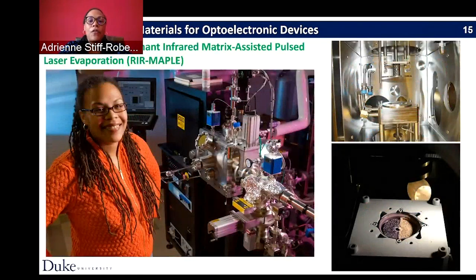But I needed a way to deposit those. And so this is what I developed during the course of my research program at Duke. And it's a variation of pulsed laser deposition. So it's called emulsion-based resonant infrared matrix-assisted pulsed laser evaporation. And this is a picture of the system that I have at Duke. I have the growth chamber and load lock chamber, and the laser is sitting in the black box. And this variation of pulsed laser deposition will allow the control and deposition of these hybrid materials in a way that's very difficult to achieve with other approaches.